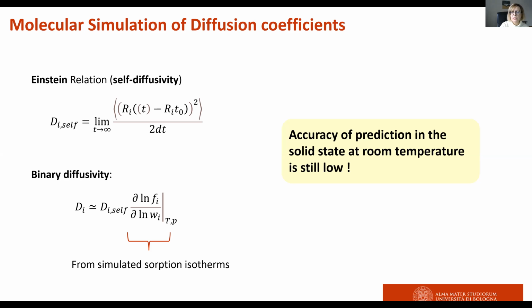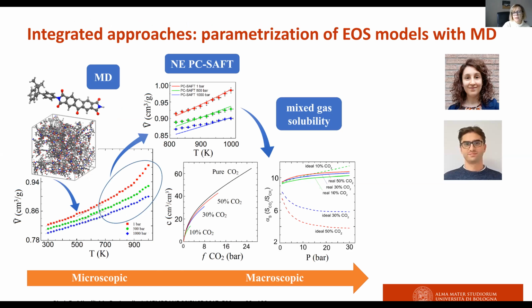The accuracy of these predictions in terms of solubility and diffusivity, especially in the glassy state, is still low compared to macroscopic techniques. Of course, you can integrate macroscopic with microscopic, and there are several efforts in this respect. For instance, you can find the parameters for polymers suitable for the equation of state modeling from molecular dynamics. And this is what we did in the case of a polymer membrane for which no experimental data were available for parameterizing the PC-SAFT equation of state. So we performed high temperature molecular dynamics simulation. We found the parameters for the equation of state, and we later used those parameters at room temperature to predict the solubility.